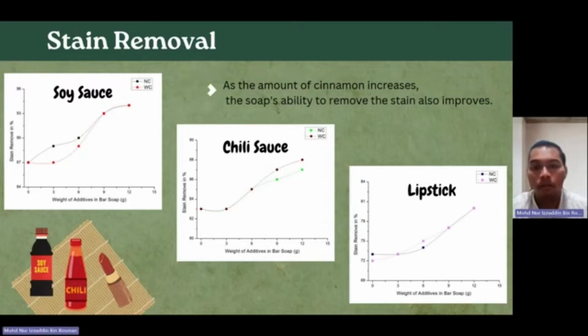But for soy sauce and chili sauce, all the samples removed more than 80% of the stain. For the lipstick, only the NC12 and WC12 samples removed more than 80%. This may be because lipstick contains wax or oil, which creates a solid adhesion to the surface.